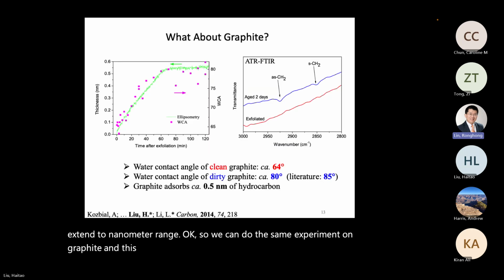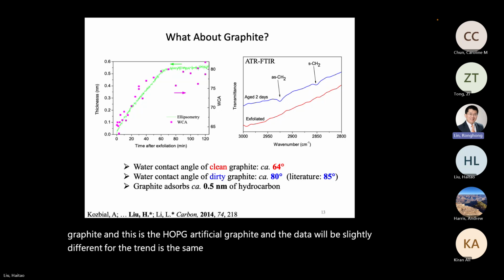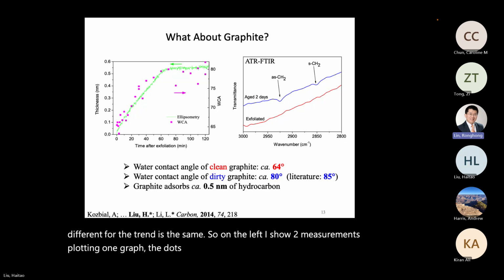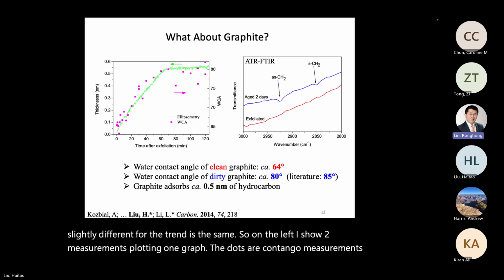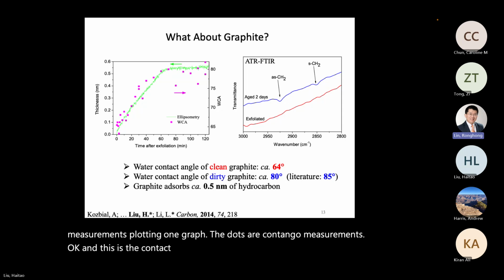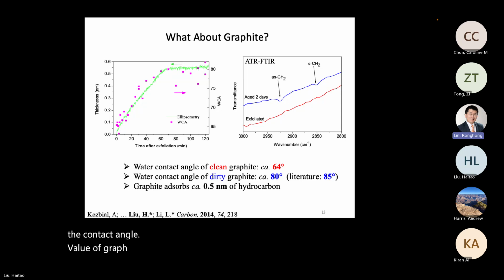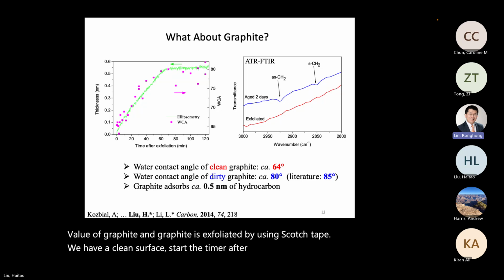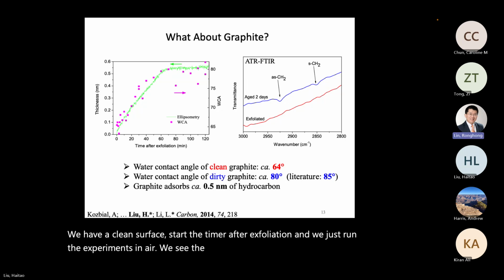This is the HOPG artificial graphite, and the data will be slightly different, but the trend is the same. So on the left, I show two measurements plotted in one graph. The dots are contact angle measurements, and this is the contact angle value of graphite. And graphite is exfoliated by using Scotch tape. So you have a clean surface. We start the timer after exfoliation, and we just run the experiments in air. We see the steady growth of contact angle.